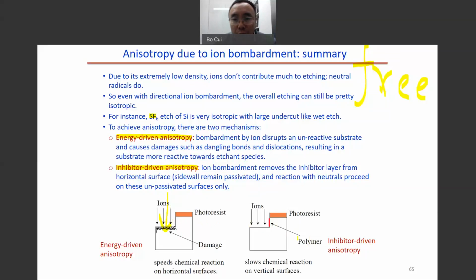So here, we have the polymer or other passivation layer on the side and also on the bottom. But the inhibitor layer on the bottom will be removed by the ion, so it leaves behind the polymer protection layer on the side wall. So this way, we can have anisotropic etching.